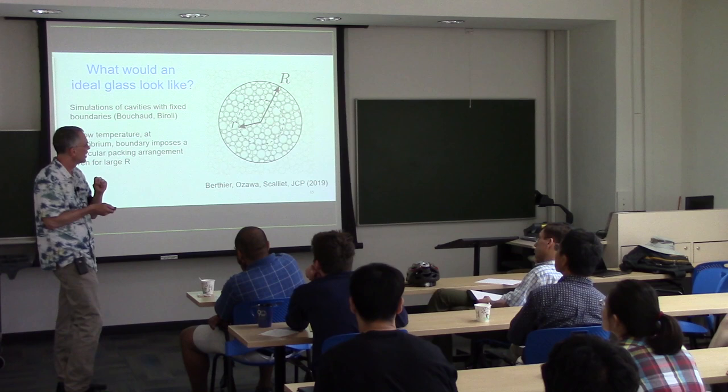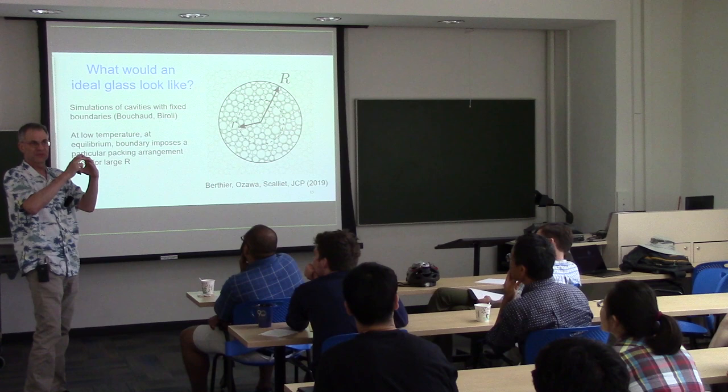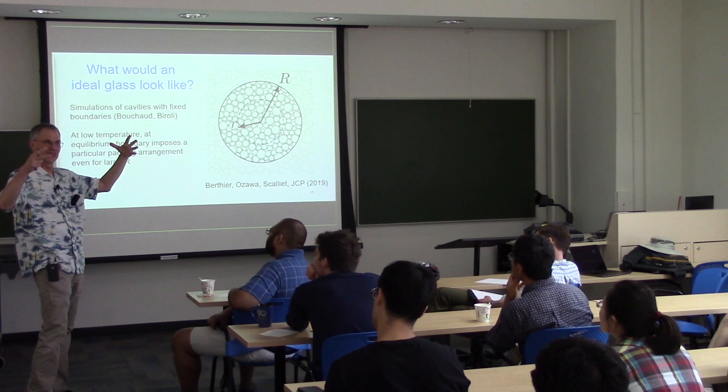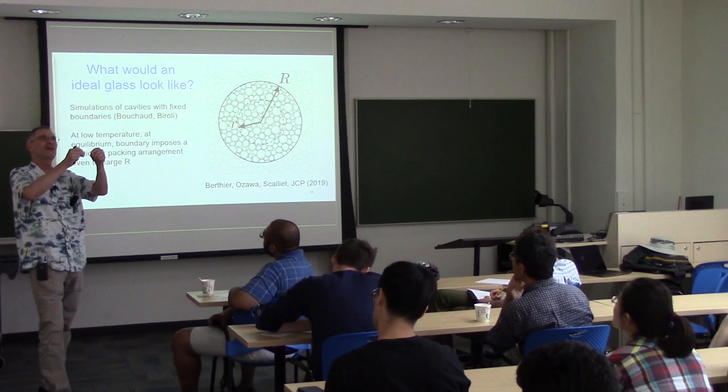And the observation from the simulations is that if you choose a small enough sphere, maybe one that's only 4 particle diameters across, you come back to the same configuration basically every time. If you pick a really big sphere, you don't come back to the same configuration every time. So for every temperature where you do this, you can find the critical size, just the right size to specify what all the packing inside this sphere is going to be like.